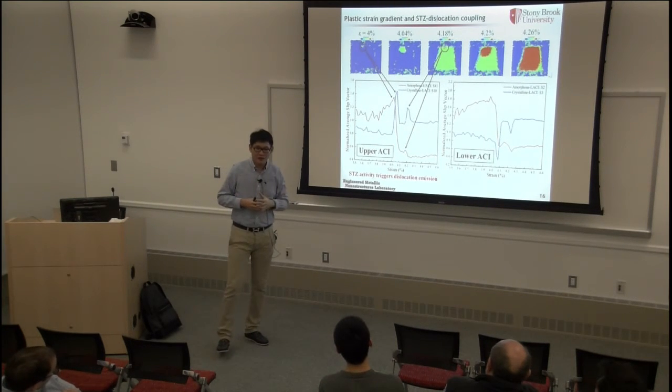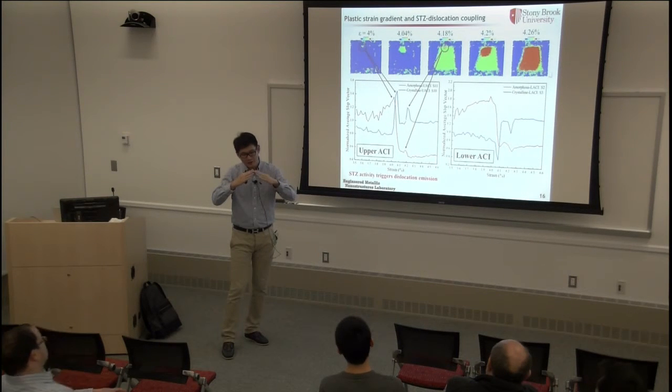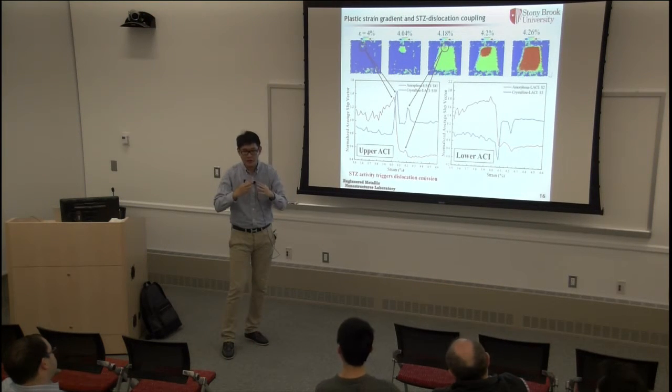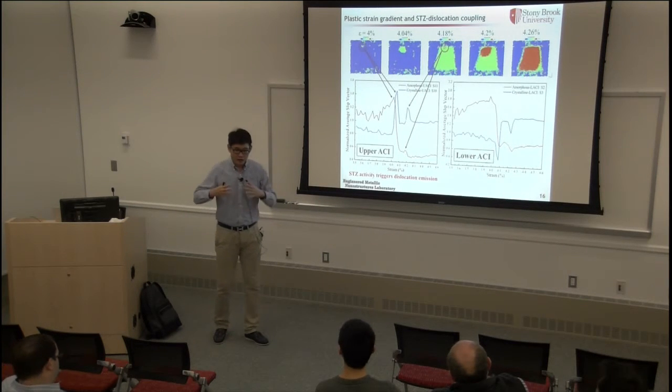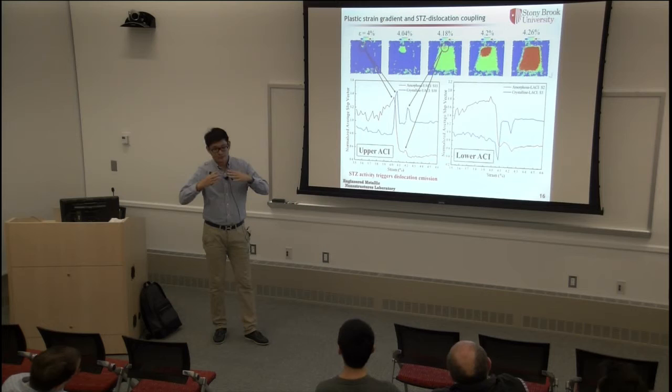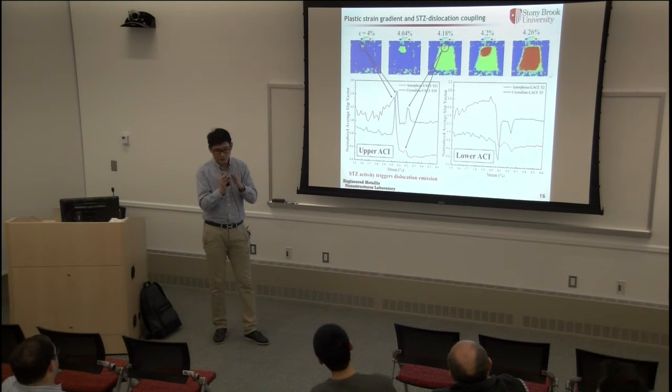I believe the grain boundary is not an amorphous layer. It is actually a result of different grains having different orientations. When they meet together, it creates a misorientation at the interface, and this leads to a grain boundary. Usually there are different kinds of grain boundary. The one with a larger misorientation angle is a high angle grain boundary. Its layer is going to be a little bit thicker because you have a lot of free volume in the grain boundary.